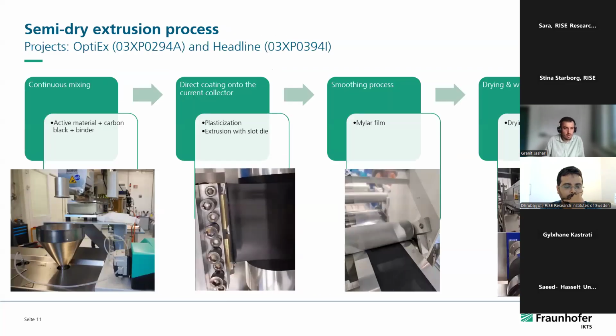To see it more, as we mentioned, it's a continuous mixing process. Here you can see we are dosing the powders, the active material, which depending on the project could be NCM or LFP, or on the anode side graphite, or also silicon oxides together with graphite. After the first dosing of the active material, we start with the dosing of the binder or the solvents.